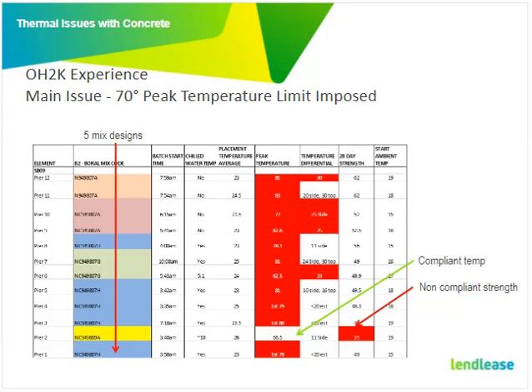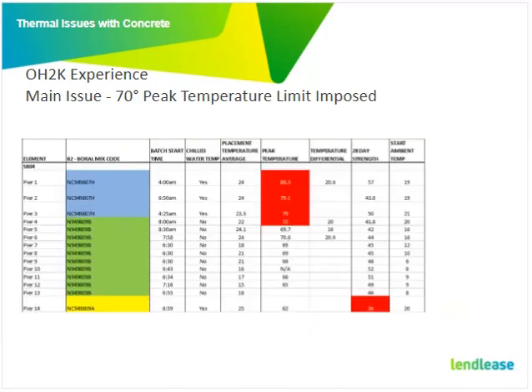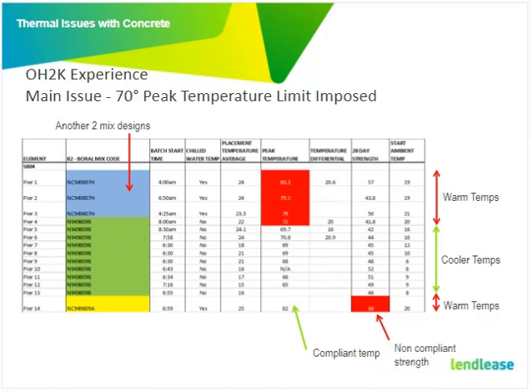But what you can see on the left is that for one bridge, we had 5 mix designs. So how can you say that that's a quality outcome? Look at the way we were forced to start with one mix that didn't comply with the peak temperature, then another mix. Where's the consistency there? There just isn't. These are the behaviours we're going towards based on peak temperature, with mixes that have fly ash and slag in them, for an issue that's not really even going to exist. It's just not driving the right behaviours, and I think that's kind of wrong in the industry.